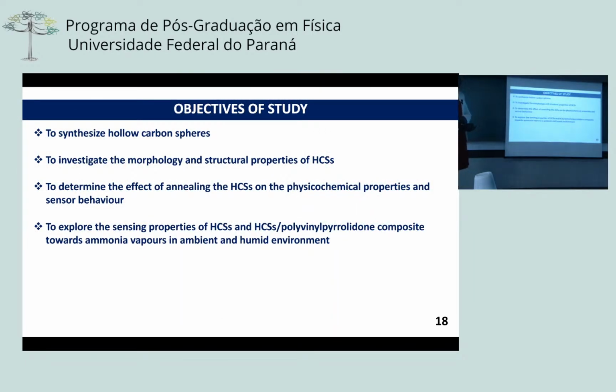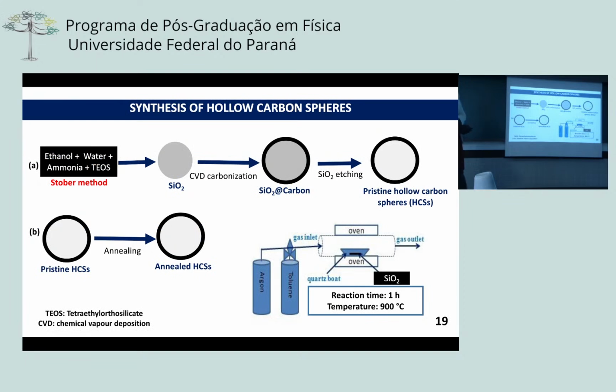The objectives of this work were to generate hollow carbon spheres, to investigate their morphology and structural properties, to determine the effect of annealing the hollow carbons on the physical and chemical properties as well as the sensor behavior, and to explore the properties of just hollow carbon and hollow carbon with a polymer composite for ammonia, both in ambient and humid environments. To achieve this, we obtained the silica using the Stöber method. The silica is solid, and we then coated it with carbon in a reactor where toluene was the carbon source. The reaction conditions were as shown here, and then we etched away the silica to get the pristine hollow carbons.